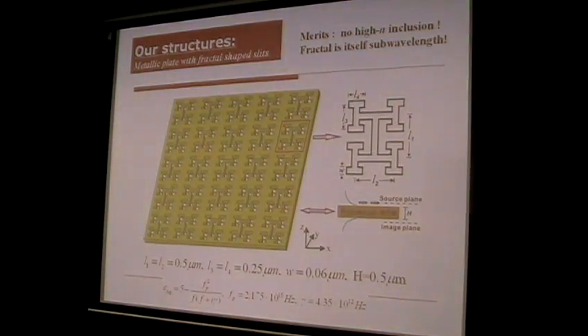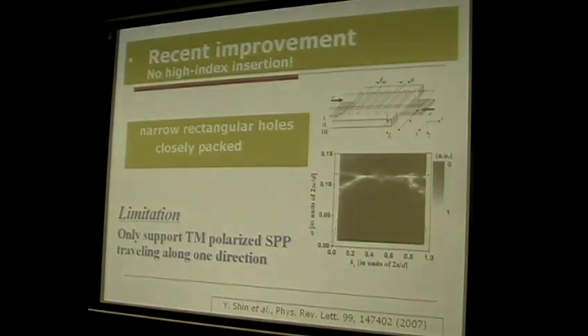So why can the slit structure not do this? Because you can find that the slit structure is sub-wavelength only along this direction, so it cannot form the running wave along the other direction. For that direction, it is not in the sub-wavelength regime, so the diffraction destroys everything. So it can only support the coupling between the two resonators along this direction, and along this direction, you will find it only performs as a TM polarized surface plasmon. So that's the key point of this structure: all dimensions are sub-wavelength.